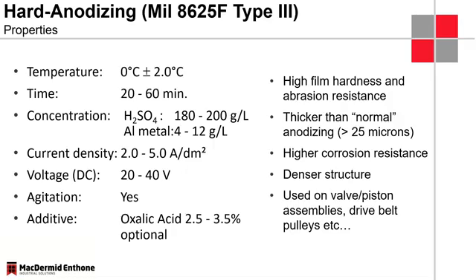The current densities here are higher, so we operate at anywhere between 2 and 5 amps per square decimeter, and again that helps us to build a much thicker layer in a faster time. The voltage, if we use higher amperages, is going to be higher again. Agitation, absolutely essential. And what we use here is a proprietary organic additive as for the type 2. Some customers decide to use oxalic acid here.